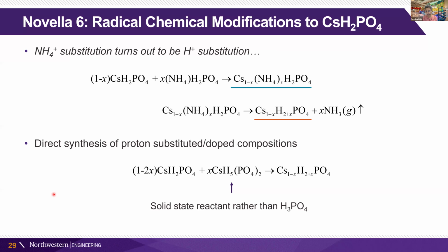After recognizing what was happening, we went ahead and did direct synthesis of proton substituted or doped compounds using cesium dihydrogen phosphate and this cesium H5PO4 compound, which allows us to create compositions anywhere in that range, in that X value, so that we can increase the proton content and decrease the cesium content to arbitrary values by making mixtures of these two compounds.